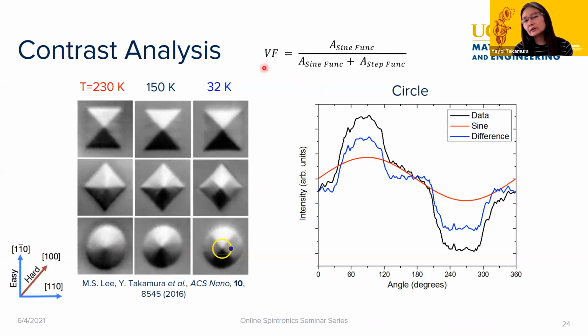And so Michael Lee decided to call this a vortex fraction, right? So the vortex fraction was basically the ratio of the amplitude of the sine function over the amplitude of both the sine function and the step function, right? And so what he did then is he took those functions as a function of angle, right, for all of these different nanostructures, and then he did that analysis as a function of temperature.